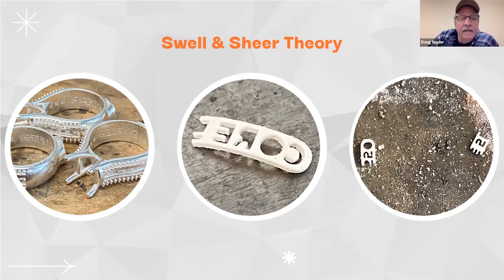So again, take a look at your design and it's like, okay, so I want a stamp on the inside. How deep does that stamp need to be and still be legible? It doesn't need to be a millimeter thick. It could get by with half a millimeter or less, depending on how much cleanup you've got. So these are some of the things that you would evaluate before you went into the design itself. And you can see that the stone settings and all of that turned out good on this ring, but just that inside stamp didn't survive, just because of the way that that thick resin attacked that thin area where it was stamped out.